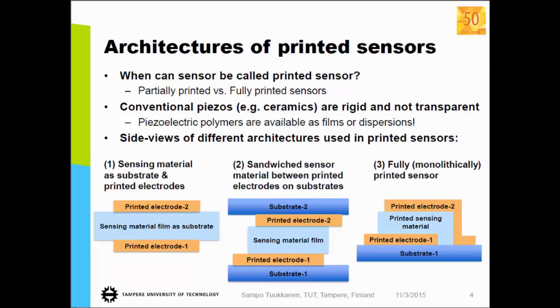So, okay, then to the different kinds of structures you can do. So basically, you can talk about fully printed systems or partly printed. So the first thing we started with is that you can select a substrate material which is functional itself, and then you can basically print only the electrodes, and you can call it a printed sensor even if it's only partly printed. Or another approach is that you can print your electrodes on some different substrate like polymer, and then put your sensing material between the two electrodes like a sandwich. Or the most interesting option would be to print monolithically all the different materials, and this is closer to the 3D printing approach.